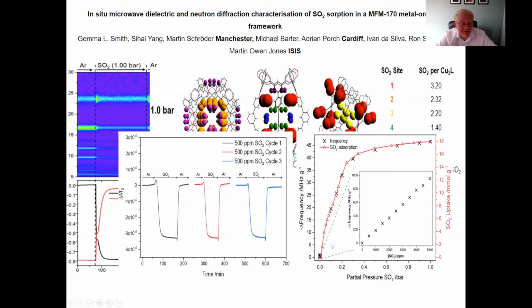And so we have a very, very good measure of SO2 absorption in our materials, and we need the combination of neutron diffraction and microwave resonance to get this full characterization of the system and get all the information that we can from that. And we do that, again, in a single experiment, dynamically under flow.